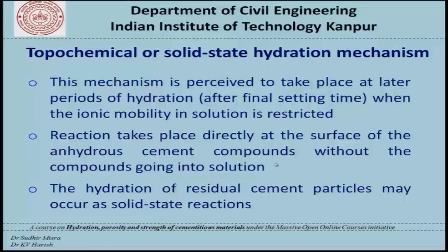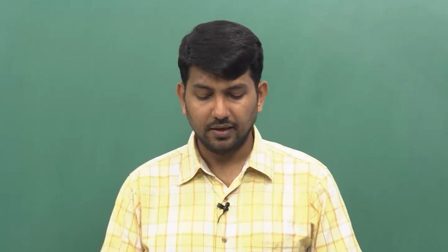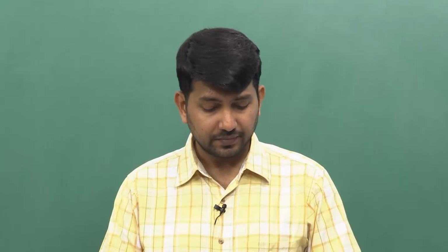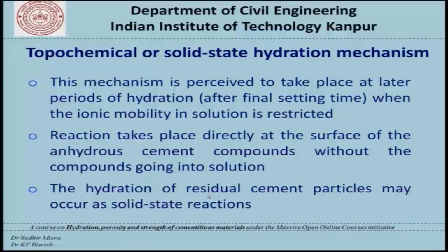This is very important because the system will remain in the wet state only for some time, and hence the through-solution mode can dominate only up to a certain point of time. After that, once some compounds are formed, then it is the topochemical mode which actually dominates. The hydration of residual cement particles may occur as solid state reactions.